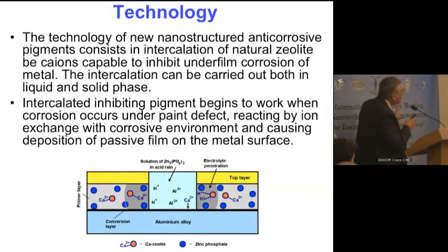Besides, our studies show that at certain conditions it can effectively interact with other inhibitors, for instance zinc phosphate, and this action will be even stronger than if the pigment is used separately, so we can talk about synergy effect.